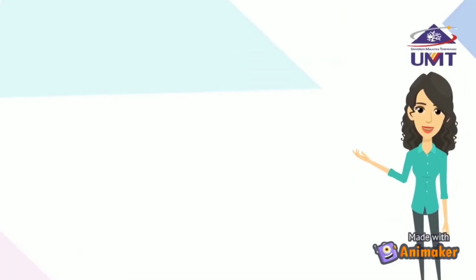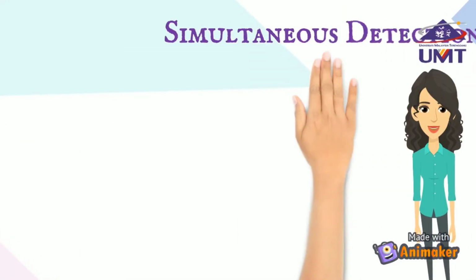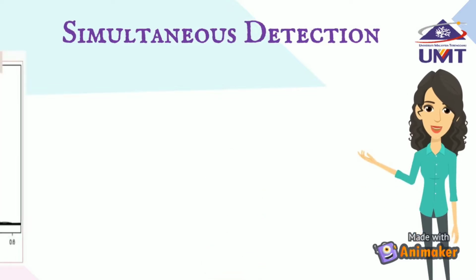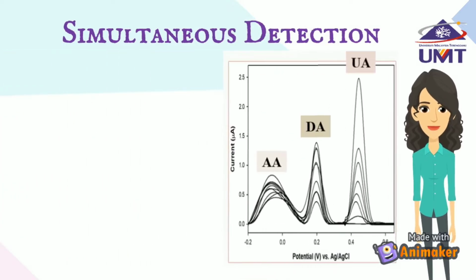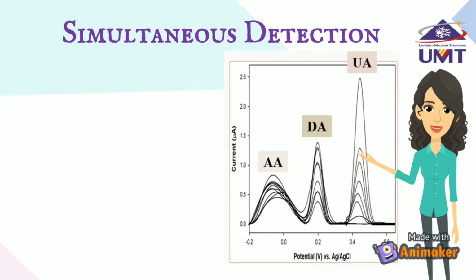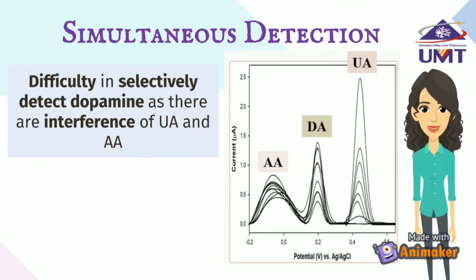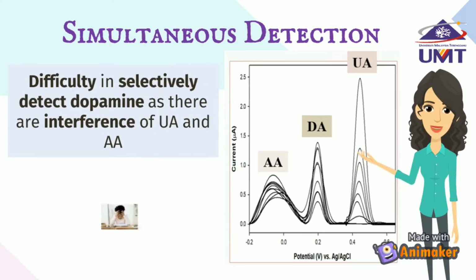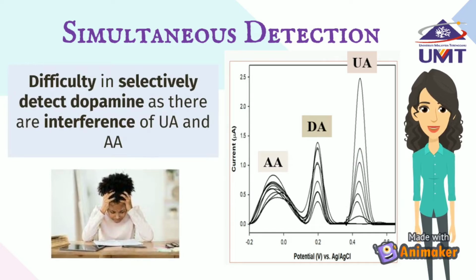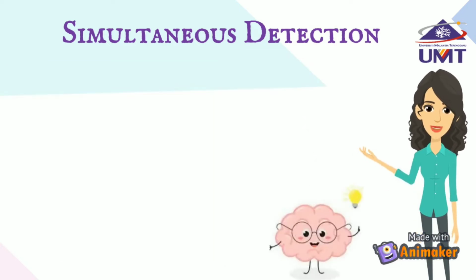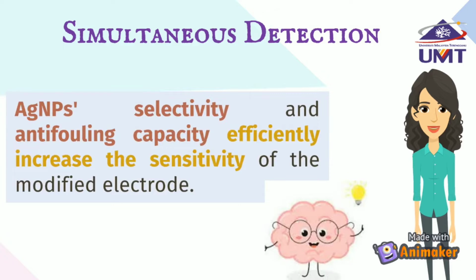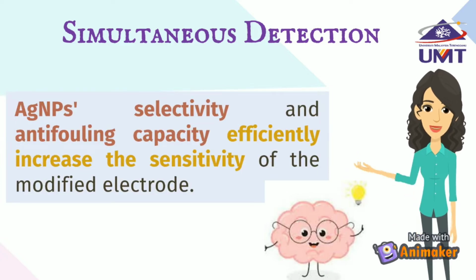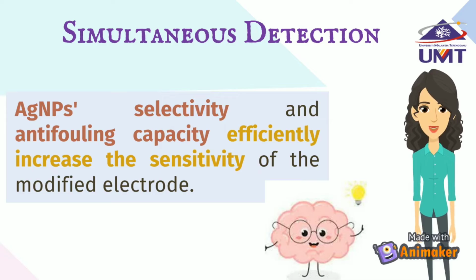During the reaction of the dopamine sensor, simultaneous detection can be observed due to the high concentration of ascorbic acid and uric acid. These compounds cause difficulty in selective dopamine detection as these two compounds have almost the same oxidation potential as dopamine. Hence, the selectivity and antifouling capacity of the silver nanoparticles are able to promote the separation of the oxidative peaks of the DPV response. Thus, the modified electrode sufficiently increases the sensitivity of the dopamine sensor.